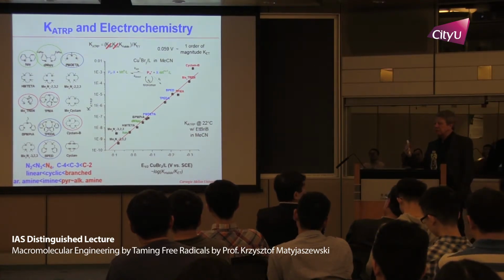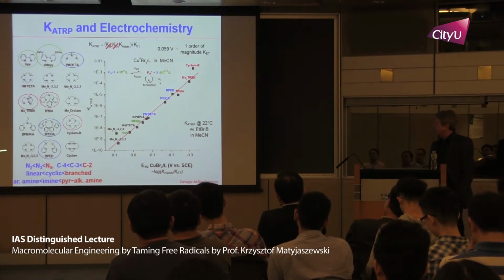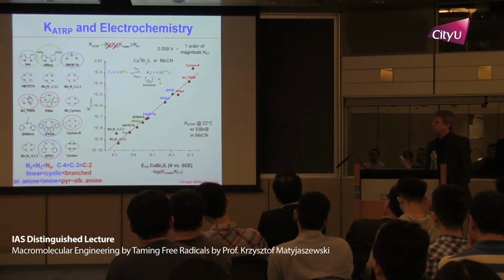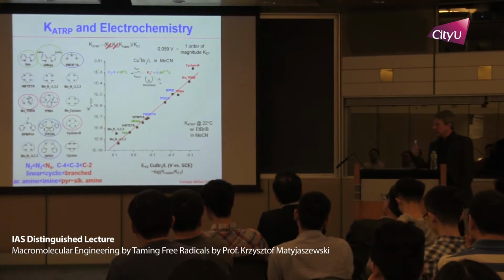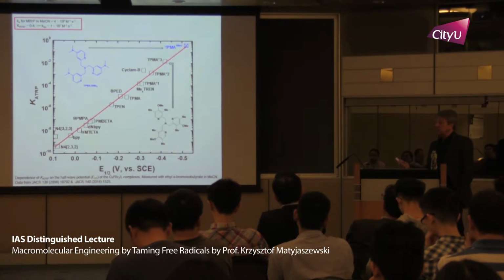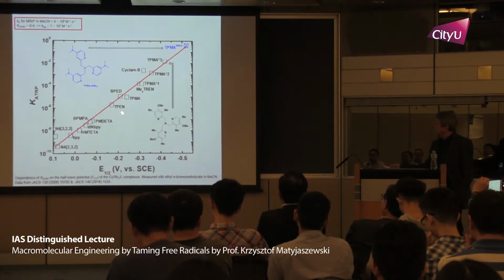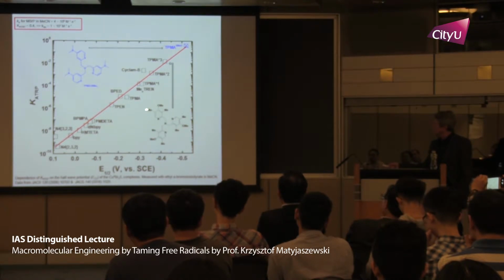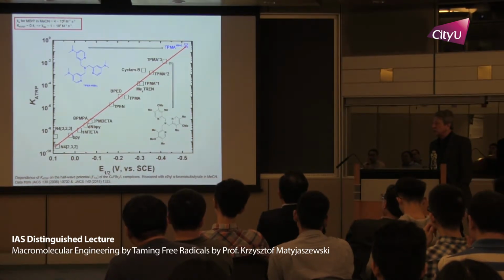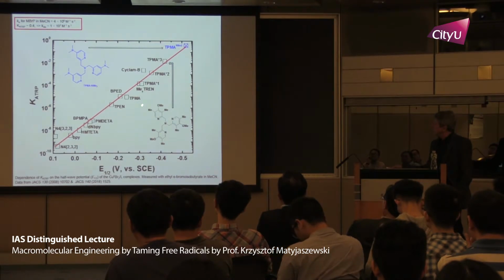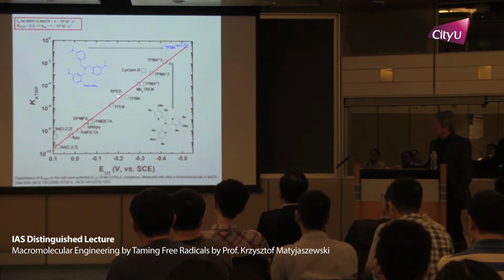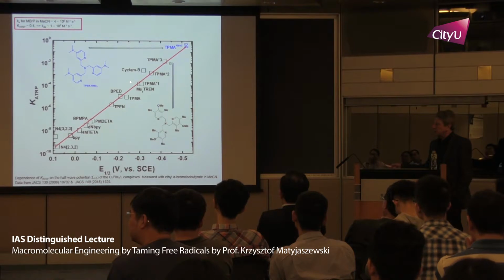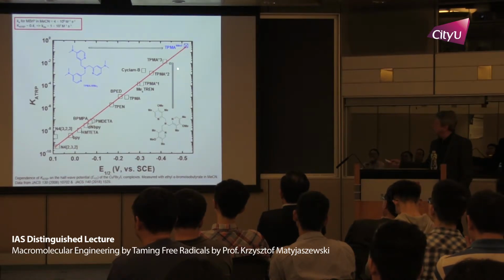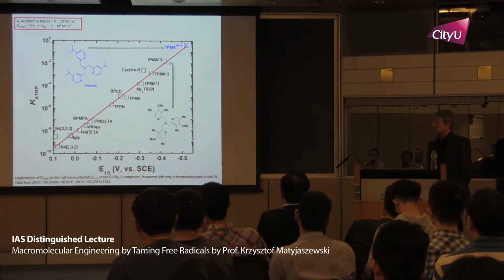So can I develop still more active catalysts? I have these principles, but I explored all of these possibilities. The idea we have is that we can sometimes use electron-donating substituents on pyridines. You have a commercial precursor of this material with dimethyl methoxypyridine. If we incorporate one of these arms, you go from TPMA to TPMA 1 star, you put 2 of them, 2 star, 3 of them, 3 star, by a factor of 10, 100, 1,000 times more active systems.